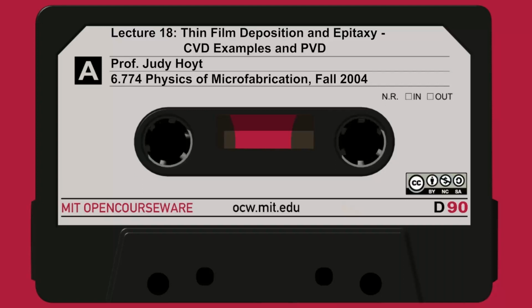If you have a point source, something that behaves like an ideal point source, you typically put it right in the center of a sphere. So you would put the evaporation source of platinum or aluminum right here in the center. Then you get a uniform flux in all directions, and you put the wafers along the circumference facing that point source. So you use a spherical wafer holder.